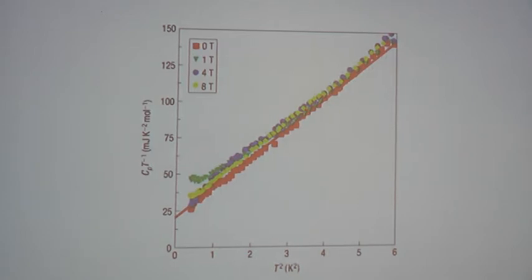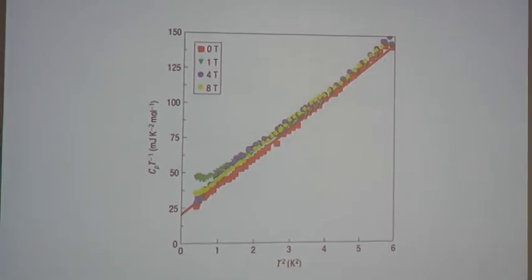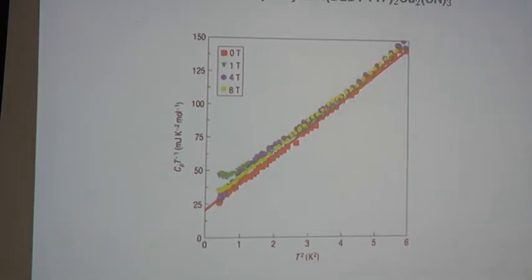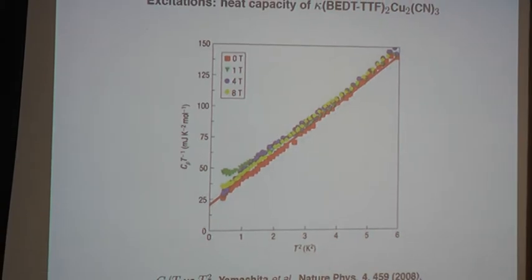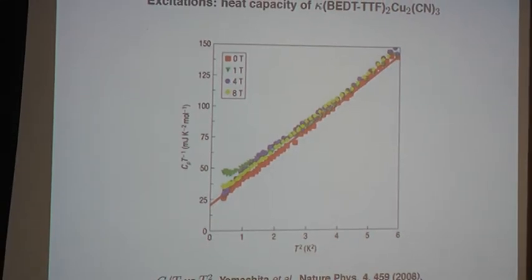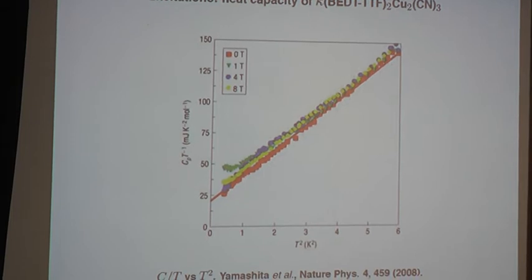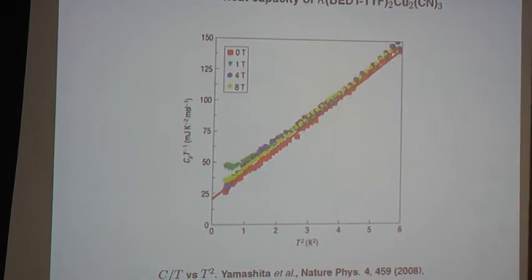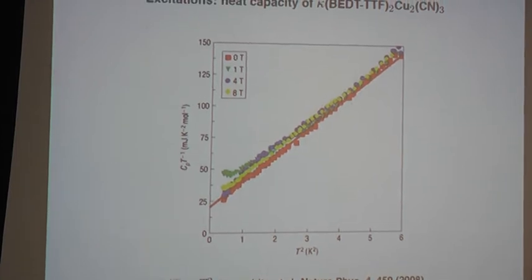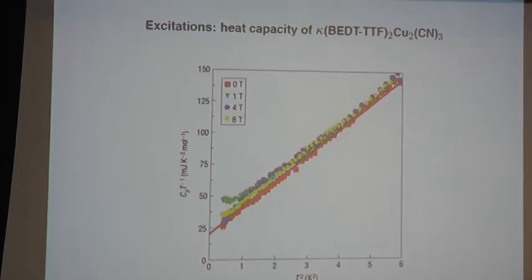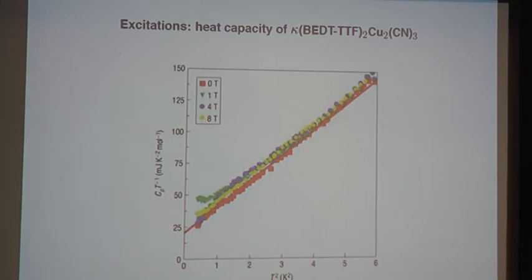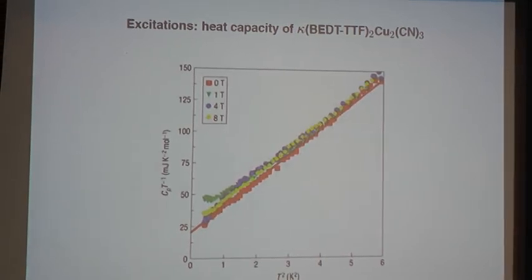But the surprising thing about this data is that this material is certainly an insulator, and so we don't have any of the usual excitations that would give us a linear heat capacity. The idea is that somehow the spin degrees of freedom are producing this contribution in a way that we perhaps don't fully understand yet.